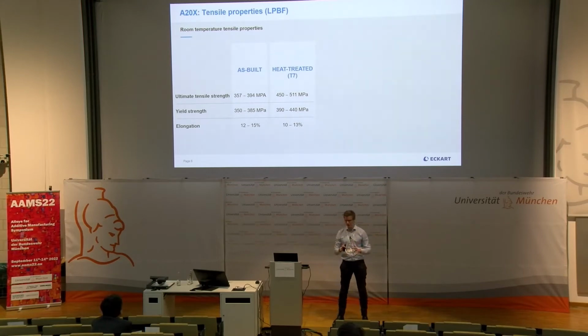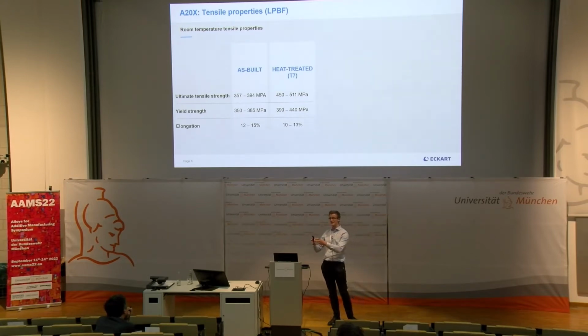So this is room temperature tensile testing results for as-built and heat-treated specimens. Now, what should be noted is that this is not peak strength, okay? So T7 heat treatment refers to solution heat treatment followed by over-aging, so artificial aging beyond peak strength. And this really is a common procedure for 7000 series alloys, for instance, which are often employed in the overaged state with the goal of balancing tensile strength, fatigue strength, toughness, and resistance against stress corrosion cracking, as opposed to just maximizing yield strength.